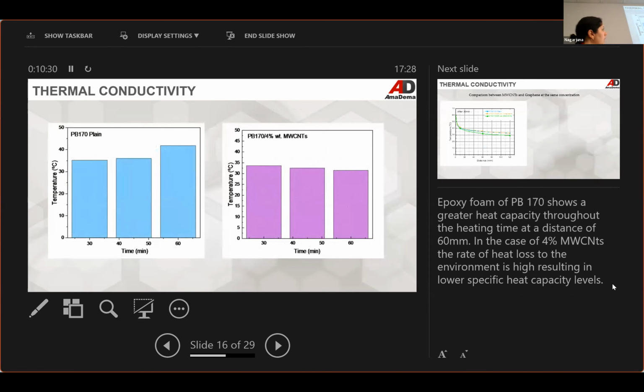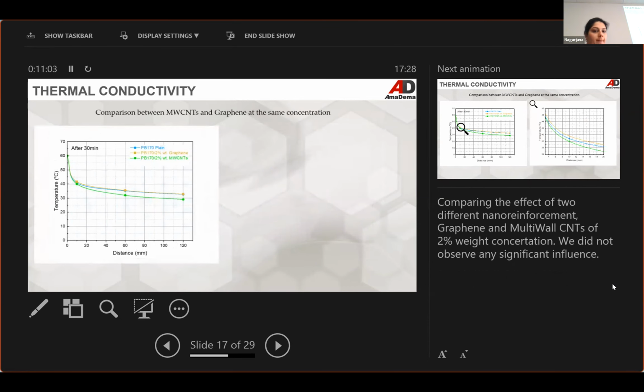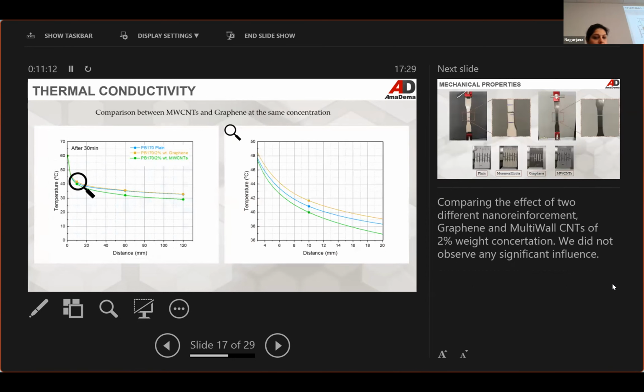Then, when we compare the plain foams with the foams that had 4% multi-wall CNTs, we've seen that the plain foams have a better heat capacity. In the case of the 4% CNTs, the rate of loss of temperature to the environment is higher due to the incorporation of the conductive nanoparticles. Thus, we end up with lower specific heat capacity levels. However, when we compared the two different conductive nanoparticles, we haven't seen any adverse effect.